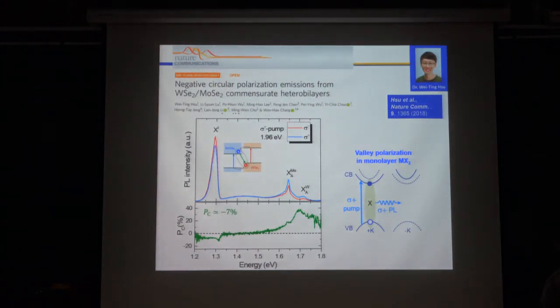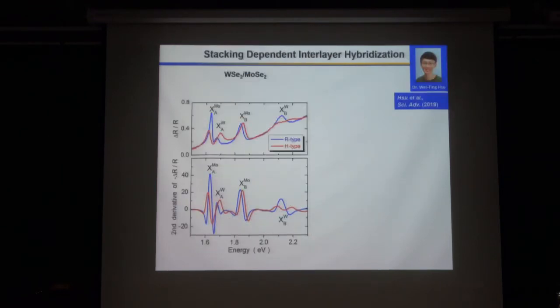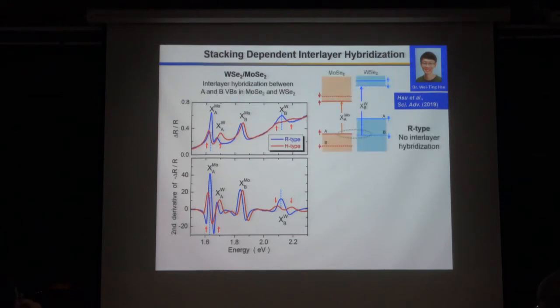So we found this material can have very different optical selection rules in comparison with the monolayer case. But I think I don't need to go through the detail. We also found that the two materials, in a commensurate bilayer structure, will produce some interlayer hybridization. For example, you can see in H-type, here we can see some splitting, and also here has some splitting. This is the conduction band, and in the band we have spin up band and spin down band. This is another material with a little bit different band gap and offset. So the two materials roughly align with different spin bands at the interface.